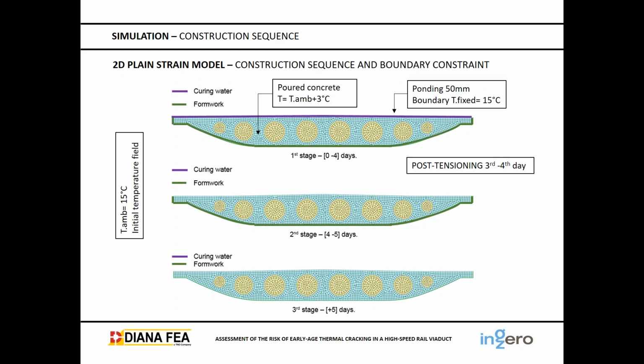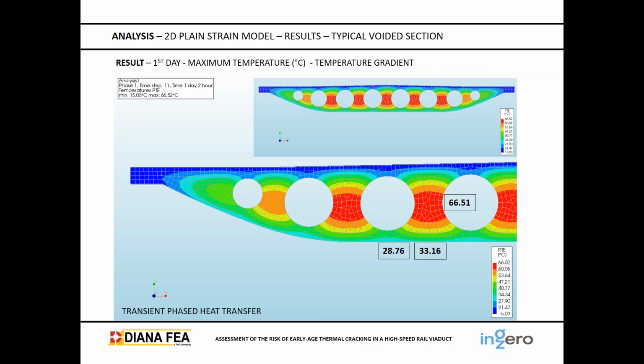Then the poured concrete, whose temperature was the ambient plus 3 degrees. We have the curing water, which we model as a boundary with a fixed temperature because we have a ponding of 50mm. Then we post-tension the slab, and then we remove the curing water, and then we remove the formwork. Okay, so with this construction sequence, we enter the results of the analysis.